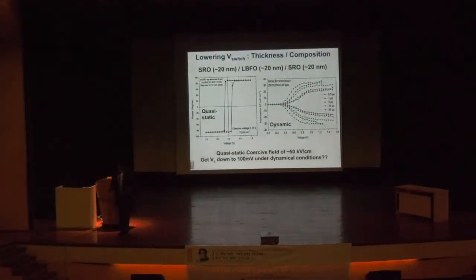Over the last year, as I said, we've been looking at how do I reduce the thickness? How do I play games with the chemical structure? And in this case, we take bismuth iron oxide and dilute it. Now, it's very much like taking your favorite drink and putting water into it, and you dilute it. Here we dilute the polarization by substituting lanthanum into the bismuth site. And indeed, the polarization comes down. Indeed, the structural distortion comes down.